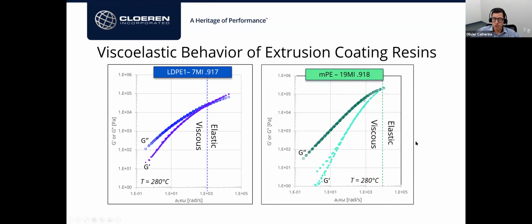Now, I picked a more drastically different material here, which is also a candidate for extrusion coating. There's a trend of using more and more metallocene grades. And the metallocene molecular structure is much more linear and also much more organized compared to this autoclave LDPE. And as a result, you see the viscoelastic behavior is quite different. We have a melt elasticity, sorry, which is very low in the terminal region. And we have a much greater delay in frequency for the crossover point. Actually, here we can barely see that crossover point in the range of frequency that we studied the material at.